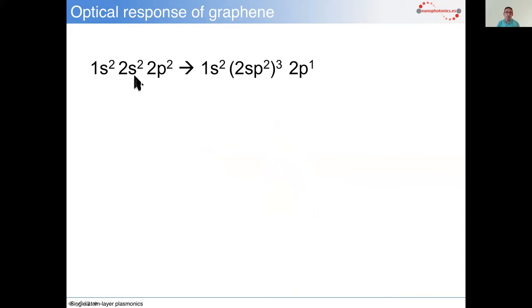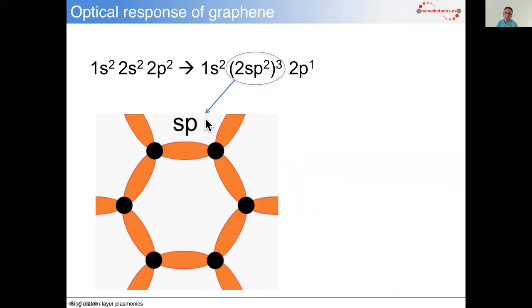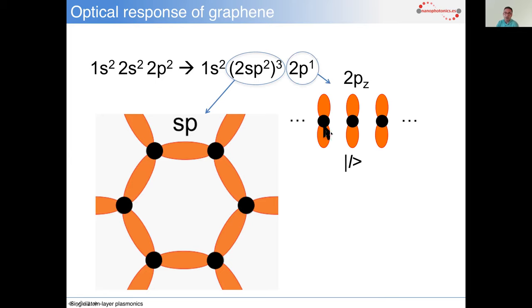So first of all, you have the electronic structure of the carbon atom, and then due to hybridization, you have these sp bonding orbitals, and then you also have one orbital that is sticking out of the plane of your screen here. Now this orbital has one electron per carbon atom, but it is doubly degenerate, so it allows for two of them. So each atom has one of these 2p orbitals sticking out of the plane, and you can represent, to a good approximation, this material through a tight-binding model in which each atom is just one site. As I said, it's a doubly degenerate